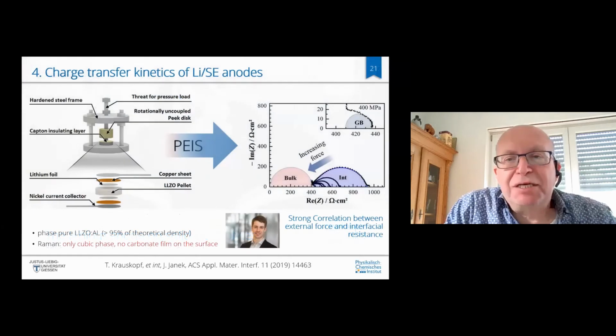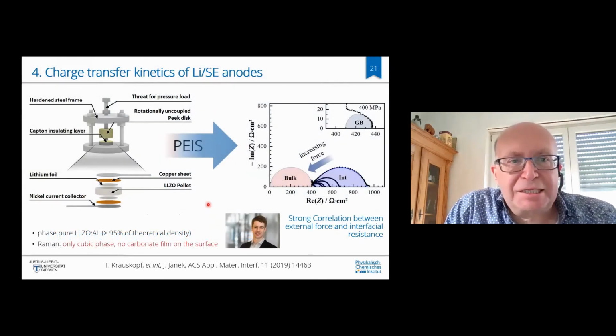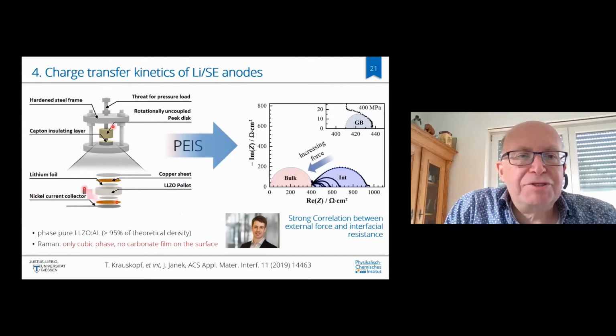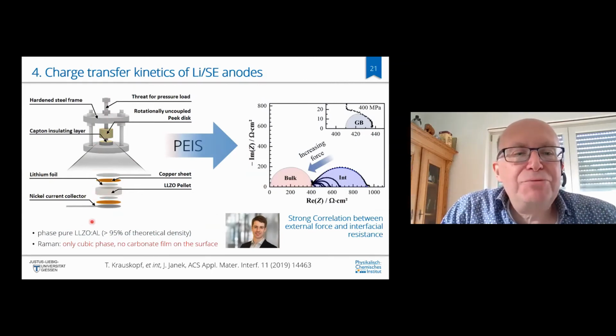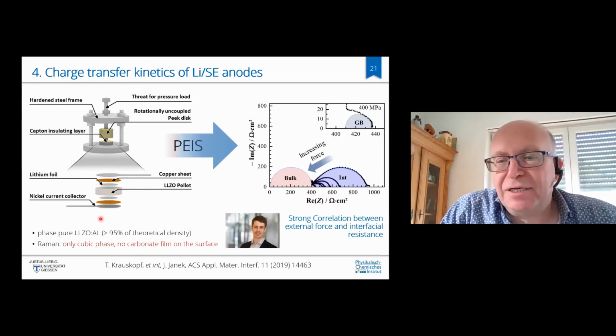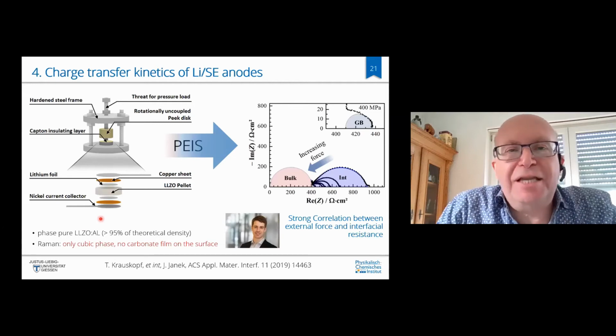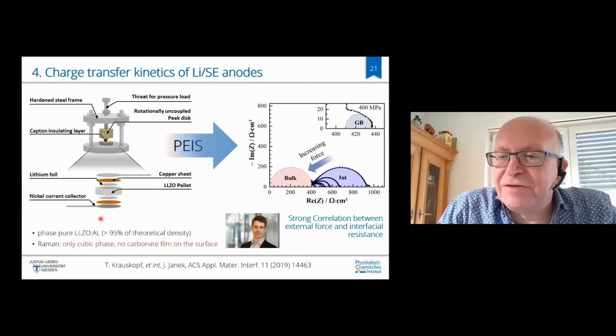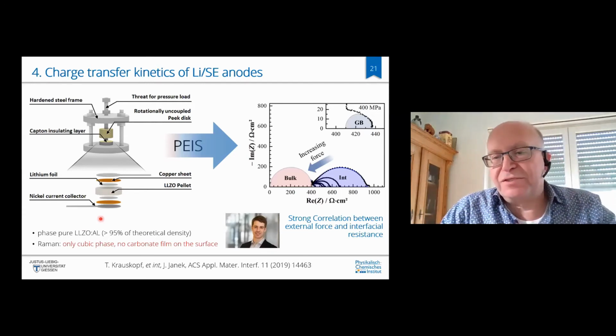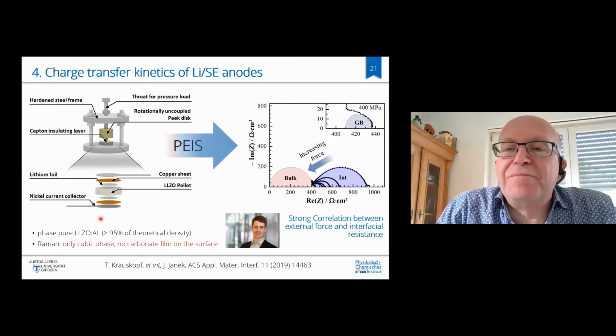Now, what we did is we studied the lithium metal deposition and dissolution as a function of pressure. So we have a device where we can control temperature and the pressure, and can measure also the pressure that is being exerted by the cell. And we chose lithium garnet as the model type solid electrolyte, because this is virtually stable against lithium metal. So we wanted to use an electrolyte that is stable versus lithium metal. All the thiophosphate and sulfide electrolytes form an SEI, which is of course a side reaction, but we wanted to see an electrolyte that is thermodynamically virtually stable.